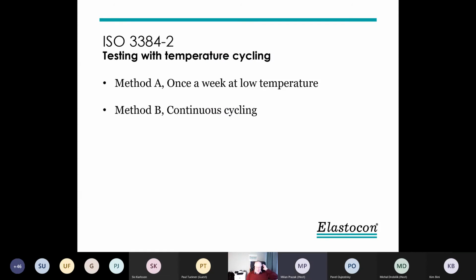Then we have another type of testing with relaxation. That is part 2 of the standard, where we have introduced temperature cycling. In the ISO standard, we have method A. We do it once a week, go down to sub-zero temperatures to see if you still have some sealing force. We can do method B, where you do more continuous cycling, then you get a little more dynamic effect as well.